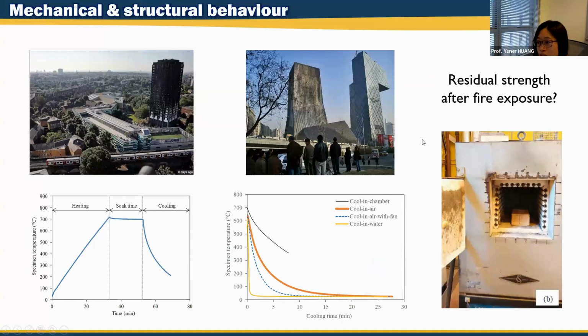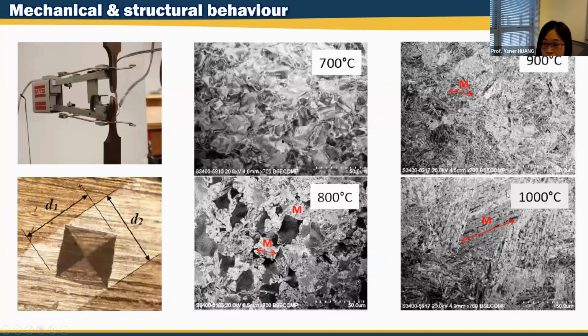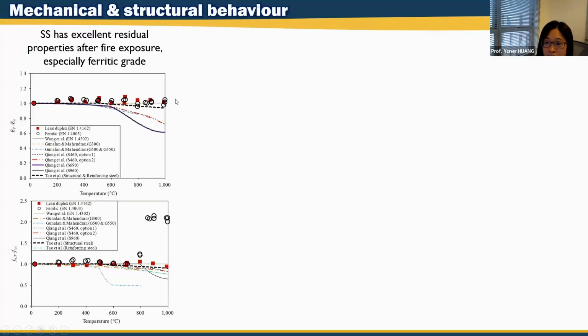And then for the post-fire behavior, we are interested to know what is the behavior of lean duplex and ferritic after fire exposure. So we did experiments to look at the microstructure and also the hardness after it has been exposed up to 1000 degrees Celsius, and we can clearly see the behavior is different. You can see these dots are our test results, and the other lines are the existing design rules for other materials.